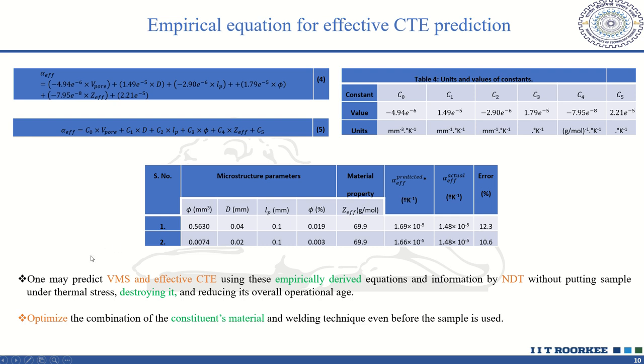So we can conclude that a composite sample can be scanned using a non-destructive technique to give the microstructure properties, that is pore shape, size, location and total porosity content, given its constituent material. So one may predict the VMS and effective CTE using these empirically derived equations and information from the NDT without putting the sample under thermal stress, destroying it or reducing its overall operational age. One may also optimize the combination of the constituent materials for the welding technique even before the sample is used.